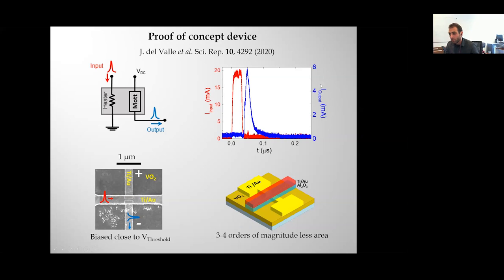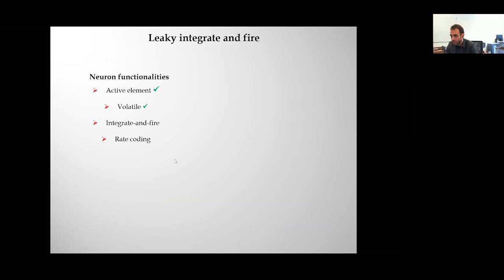We are thinking of ways that we can achieve that, getting a larger output than the input, which would make a standalone component that can be used as a neuron. So it's active, it's volatile. What about the other functionalities, integrate and fire? When you are doing capacitive integration, the characteristic timescale of integrate and fire is given by just the RC constant of your circuit. In our case, it's given by the characteristic thermal time of our device, which is given by the specific heat. Here you have the warm-up time, how fast the device warms as a function of the input current. You can see that it's always around 100 nanoseconds.